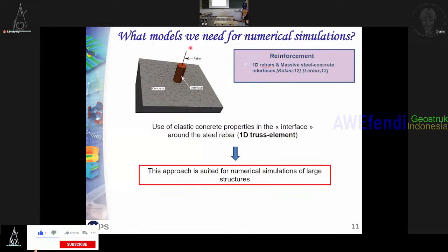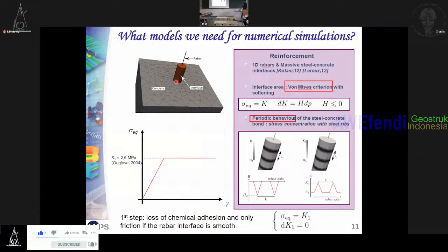So for the modeling of the rebar, we use just one truss element. But if you have one truss element, it means that the nodes should be the same between concrete and rebar, which is not correct because you should have cracking. So what we do is use a volume around the rebar, and this volume is representative of the interface between the rebar and the concrete. With this technique, you just mesh concrete in 3D and rebar in 1D, so it's quite easy to use for structural calculations.